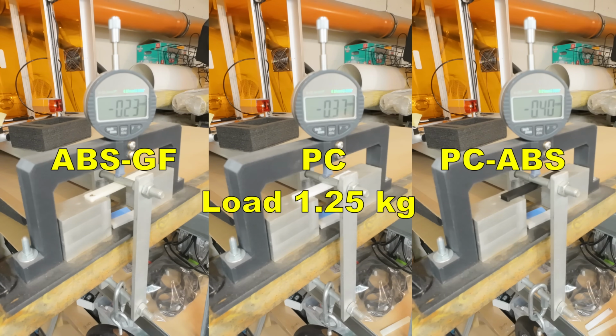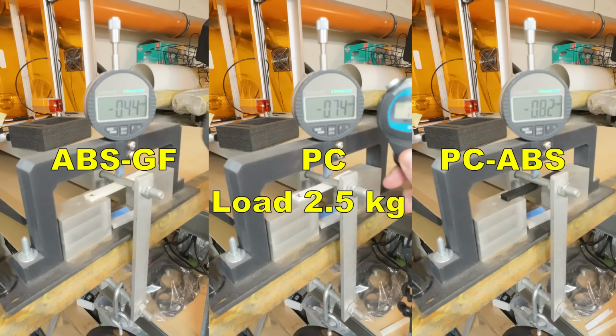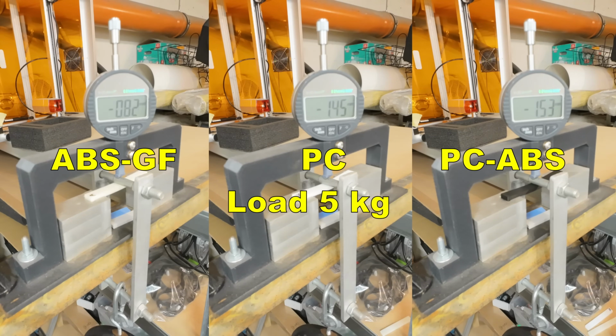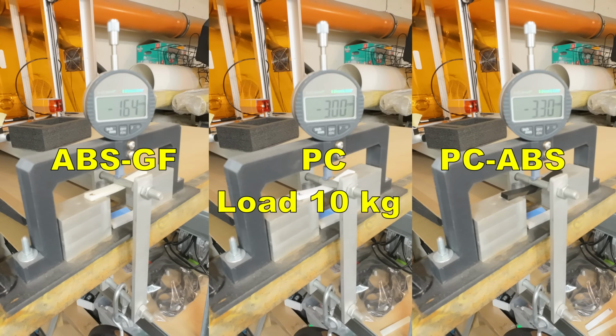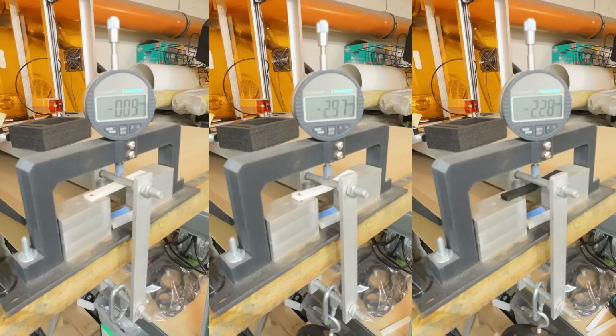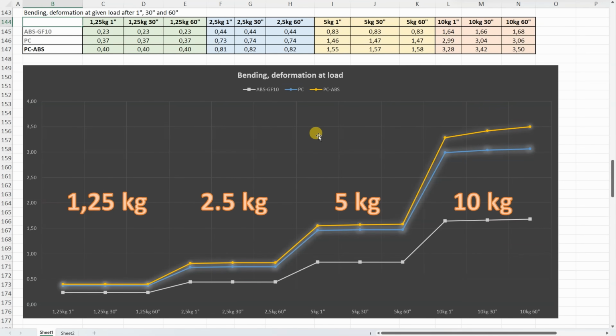3-point bending test. Distance between supports is 50 mm, side by side all three materials, and I'm recording the deformation after 1, 30 and 60 seconds. And currently you can see the deformation under 10 kilograms. For me this is a very important test, and very minimal deformation we can see on the ABS-GF. PC and PC ABS are very similar. Only under 10 kilograms we can see more additional deformation under this 1 minute on the PC ABS.